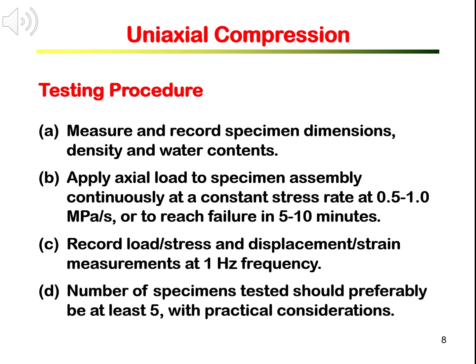To start the test, make sure you measure and record the specimen dimensions, densities, and water content conditions. In terms of dimensions, you will need to measure the diameter and the length several times at different locations. For example, diameters at different heights of the specimen. Water content should be recorded as room dry, saturated, or natural condition.